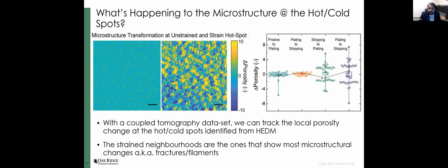If you track the bulk average of porosity change during cycling, you get this square plot here marked by the solid line. But if you track the porosity changes at these hot spots and cold spots that we identified, you can see that as you continuously cycle this cell, they deviate more and more from the mean value of this pellet. And so it is these regions that are essentially the regions where failure is occurring.